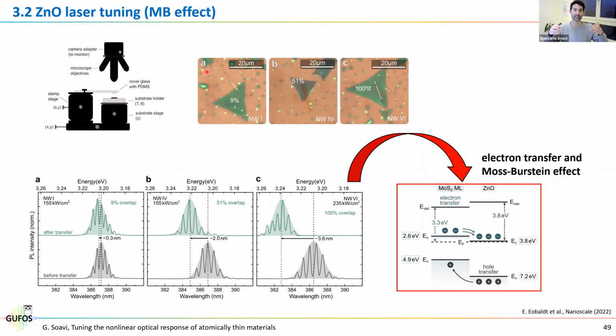And you can clearly see it because when you have only spontaneous emission, the entire nanowire is bright. But when you have lasing, you have light only at the two facets. And even though lasing is coherent, so you should not see it, you always have some divergence. So basically, you see the cone at the output of the facet that goes up.